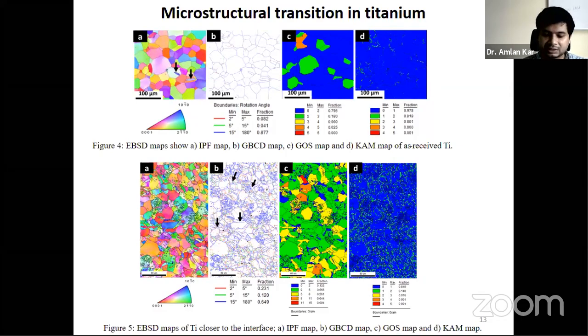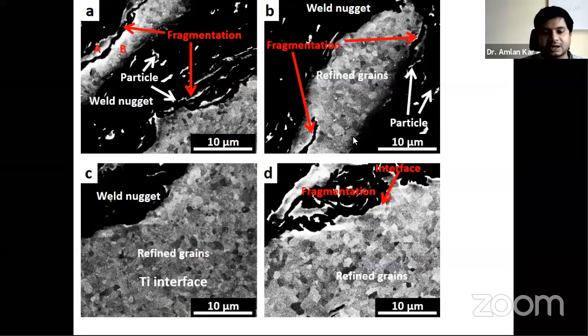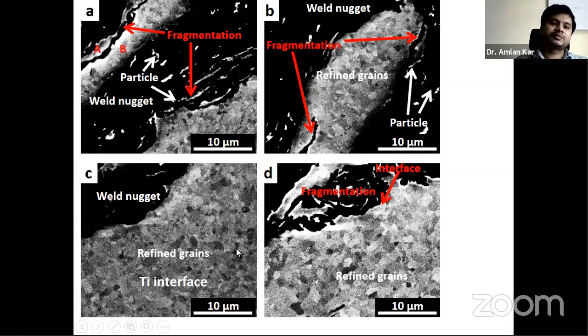So as we are moving from the base metal to the interface, there is certainly an increase in the strain and the strain rate. Due to the increase in the strain, there is a formation of twins because titanium has a lower number of slip systems. So twinning is another mode of deformation. And at the interface, we can see there is a possibility of formation of an adiabatic shear band.